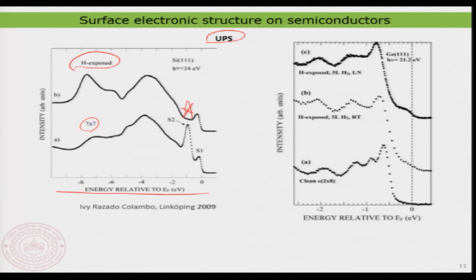If you recollect, S2 originates from the adatom on the surface. So, this indicates that when you deposit hydrogen on the surface, all the surface atoms are getting passivated or saturated by the hydrogen atoms. So, the surface is saturated, and therefore you kill the surface state S2. But S1 comes from a silicon atom that is sitting a little bit inside and not on the very first layer, and therefore it is not affected. So, it persists, but the other one is killed just because you have the hydrogen passivation. This is clearly something very interesting.